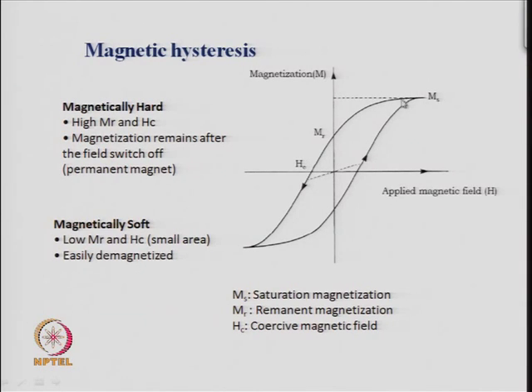So, if you have high MR, okay, and high coercive field, that means very difficult for the magnet to lose its magnetization. So, high Hc means you have to go to very high magnetic fields before the magnetization goes down to 0. So, basically the area of the loop will increase when something is magnetically very hard, and not only that, the breadth of this loop will be very high, because Hc will be very high. So, typically a permanent magnet or a ferromagnetic substance will be magnetically very hard. It will have a high remanent magnetic field and it will also have a high coercive field.